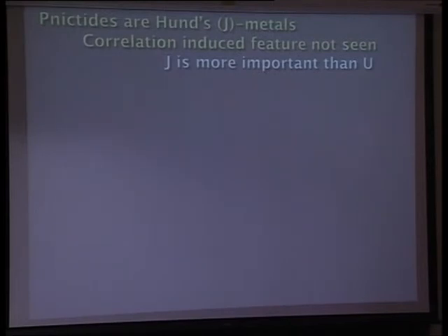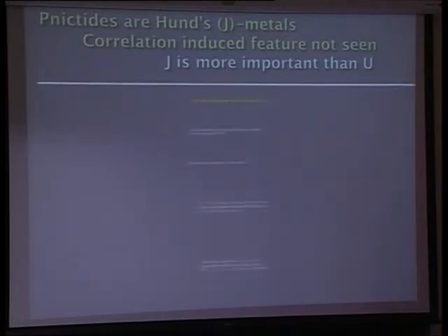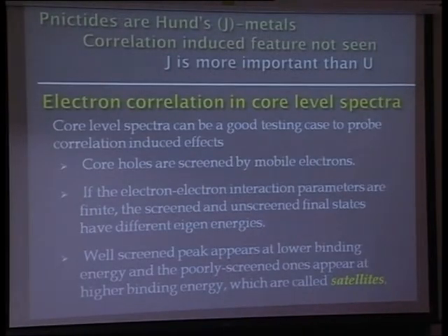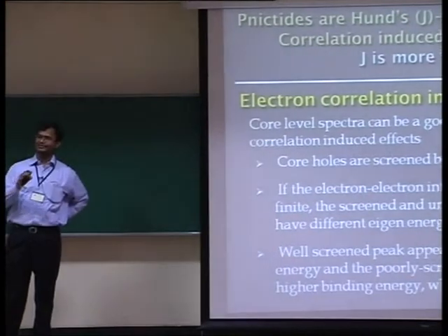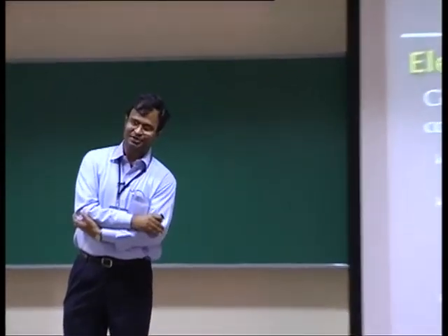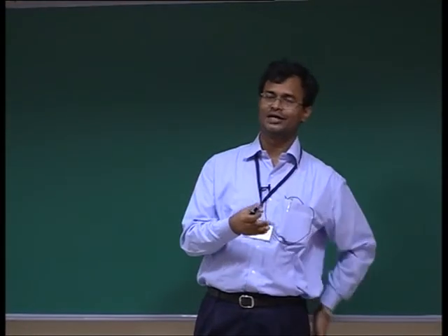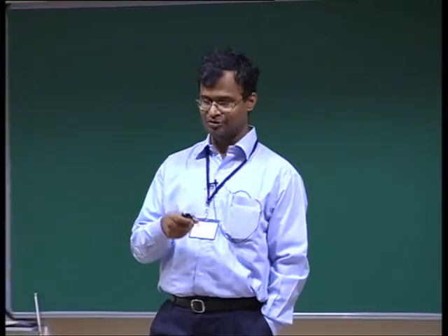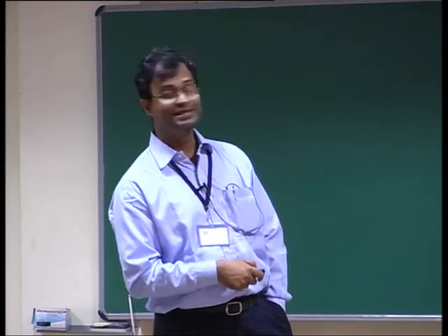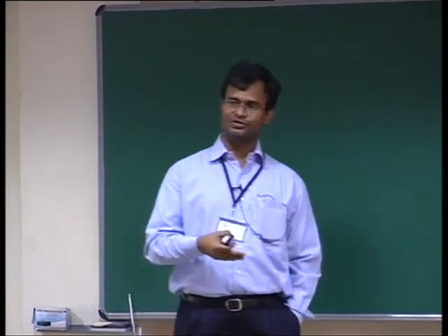First I wanted to look at, as you know, these pnictides have been described as Hund's metals, I mean that electron correlation is not so important. So we wanted to look at the core level spectrum a little carefully, because if you have electron correlation, normally you would see a signature of the lower Hubbard band when you look at the valence band spectrum, okay? But sometimes if you have many electronic states contributing, with bonding, anti-bonding features and so on, it may become more complicated to really look at the correlation-induced feature for the lower Hubbard band.